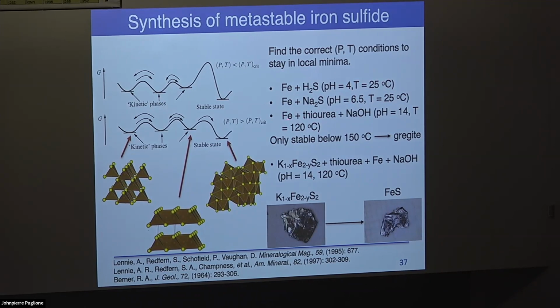So you can mix iron. You can use sodium sulfide as your sulfur source, but we also use thiourea. You add sodium hydroxide as a mineralizer, and that also increases the pH to 14. If your temperature is relatively low, below 150, because above 150 you start to form other phases, so let's say 120 is a good temperature, you can form polycrystalline single phase Mackinawite pretty easily.